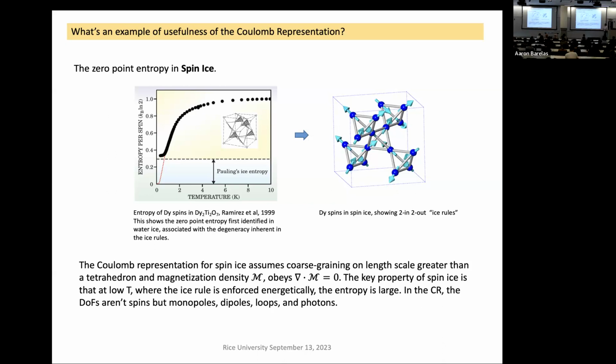And so this shortfall of entropy is extremely close to Pauling's ice entropy, which, you know what ice is. Ice has a perfectly ordered oxygen lattice, but the hydrogens are completely disordered. It was a big problem back in the 1930s, and Pauling solved it by showing that there was a degeneracy. Hydrogen could be in one of two positions, close to or far from an oxygen. And that's basically the Ising model for spins on the pyrochlore lattice.